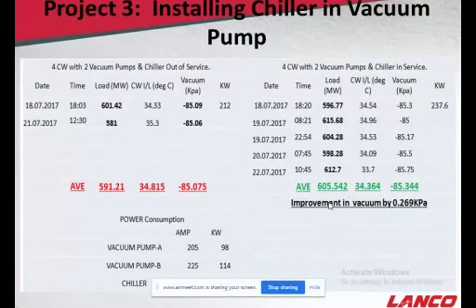These are some data from the running vacuum pump for the load and vacuum improvement. There is a slight increment in the power consumption due to the chiller, but it was well compensated by the improvement in the vacuum of 0.269 kPa under two different conditions, that is, without chiller and with chiller, with the vacuum pump running.